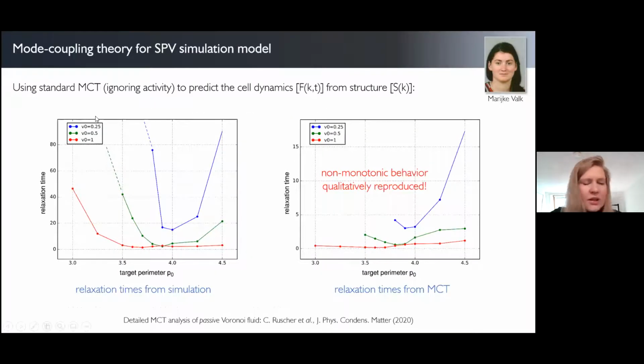And so here you see the results. On the left are the simulation results, where we plot the relaxation time as a function of this preferred cell perimeter. In the interest of time, I won't say too much about it. I'll only point out that we see this non-monotonic behavior here in the simulation for the dynamics. And then applying mode coupling theory to these data, we get the right predictions here for the dynamics. Although the theory is not quantitatively accurate, it captures this non-monotonic behavior qualitatively pretty well.